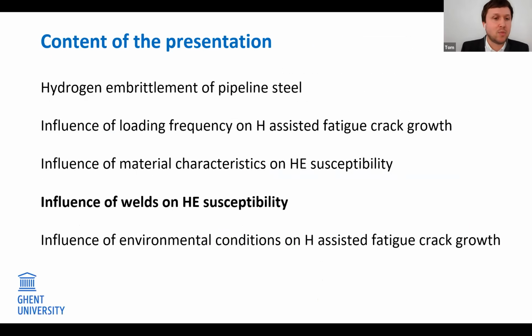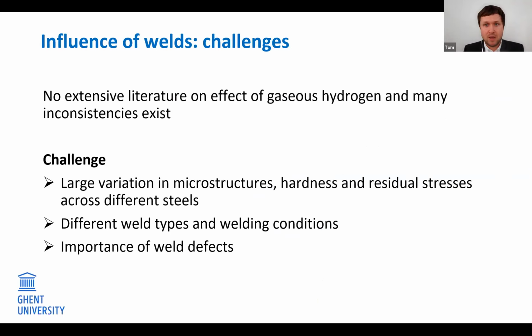Let's consider welds now, because welds are also an important factor in the distribution of gaseous hydrogen. Pipeline welds show critical features compared to the base material. For instance, stress concentrations are present due to geometrical imperfections. We also have weld flaws, and we can also have poor coating conditions. Next to that, we have critical microstructures in a weld, because we have different types of microstructures going from the filler to the base material with heat affected zones in between. Also, we have a high residual stress.